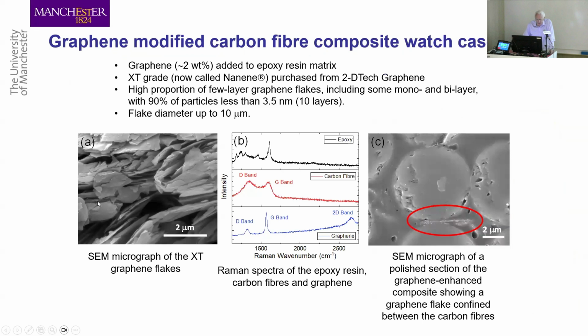We took these graphene flakes, we put them into the composite, and here are the carbon fibers. You can see the graphene flakes are sitting between the carbon fibers here. We did Raman spectroscopy to distinguish between the carbon fibers and the graphene. This is the carbon fiber spectrum, very broad, graphene spectrum, very sharp. And we could see where the flakes were inside, reinforcing the composite. So we reinforced the carbon fiber reinforced composite with graphene, essentially.